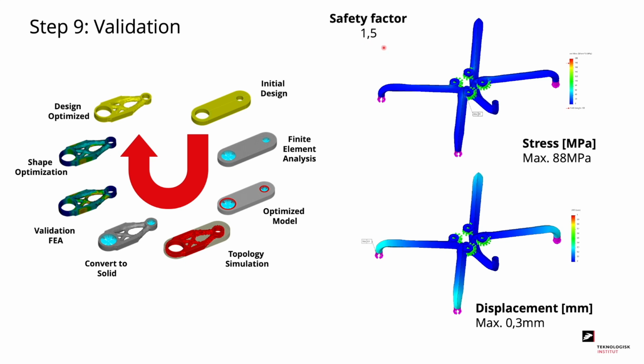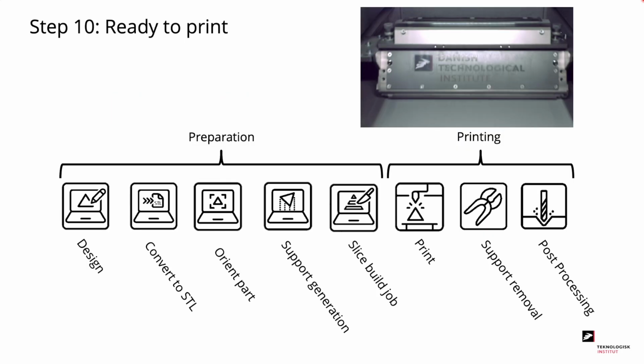Here we get a maximum stress of 88 for the robot gripper, which is well below the yield stress. We also looked at the displacement when lifting a box of 4 kilos, which this gripper will do. And the maximum displacement was 0.3 millimeters, which is acceptable for a gripper of this type. This indicates that we could optimize our design even more, maybe by reducing the wall thicknesses of our channels from 1 millimeter to 0.4 millimeters. Now we're ready to start printing.